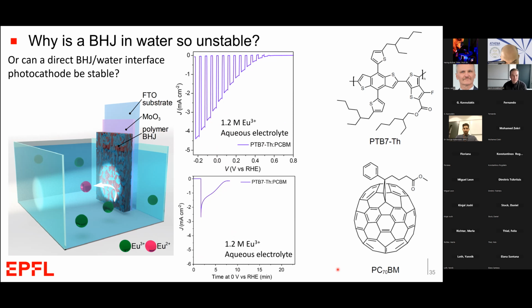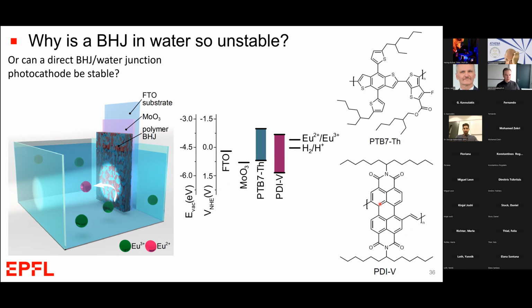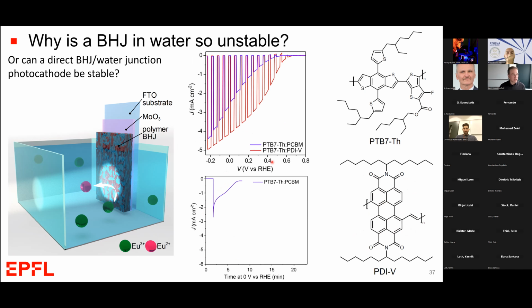Now, we took some inspiration from the literature of organic photovoltaics, which suggested that these fullerene-based materials aren't so stable. And it turns out that that stability gets worse when we put them in water. If we just change this material, for example, for this PDI-based polymer, we get much more robust performance. First of all, a little bit higher photocurrent with this PDI, and then much more stable performance. In fact, we have a little increase in the absolute magnitude of the photocurrent, because the film has a little bit of water ingress over the first 20 minutes, which actually helps the surface area for the